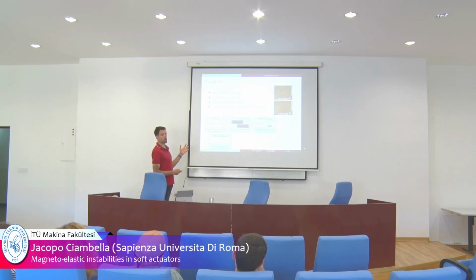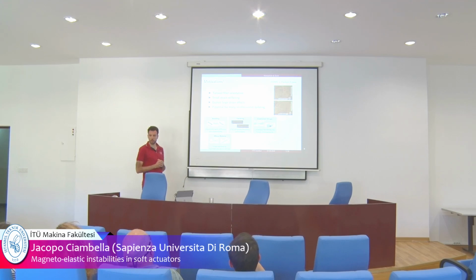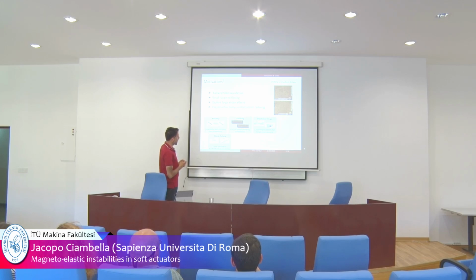But let us start with motivations of the research. Okay, so when we initially started looking at the problem, we were only interested in the mechanical aspects. So how to control the mechanical properties of a specimen by tailoring. Stiffness can be tailored by controlling the orientation of the fiber locally. And so what we wanted to do was small strain, because we started looking at this field in epoxy-based composite, so everything was small strain, and we were interested in controlling the orientation, stiffening at small strain.